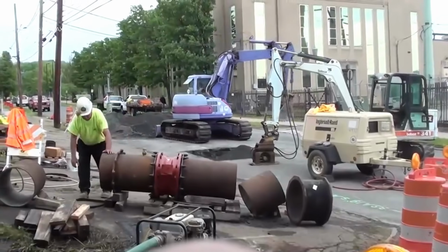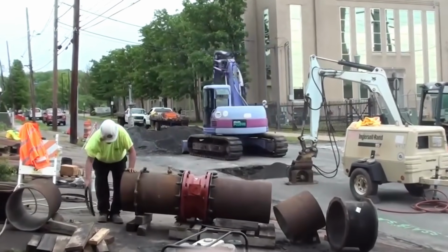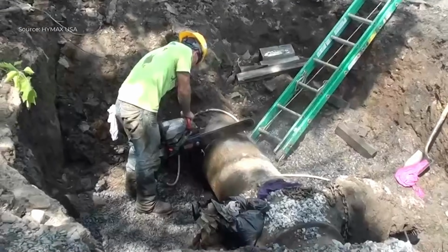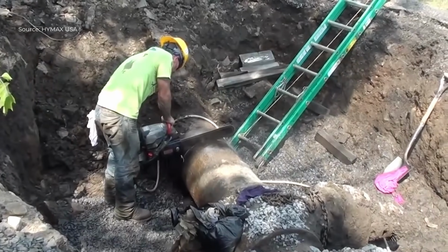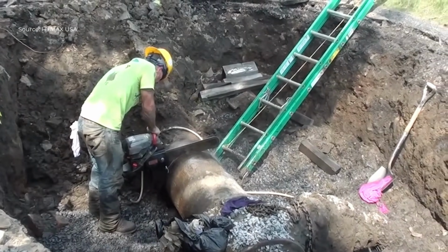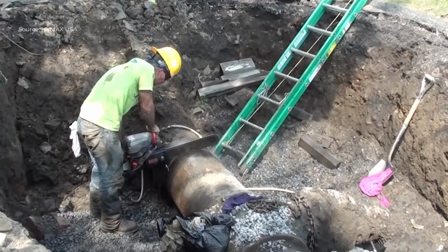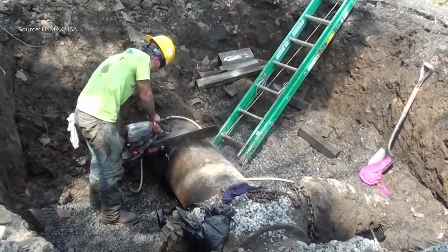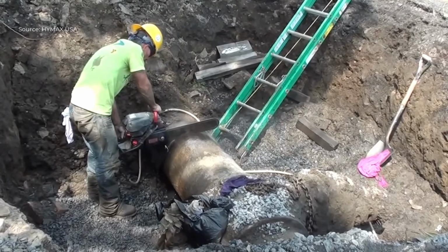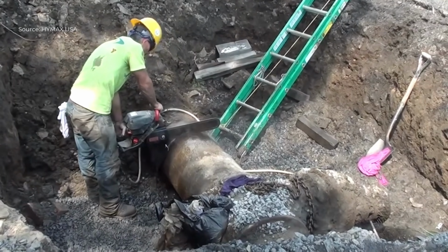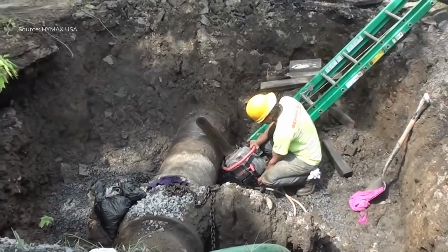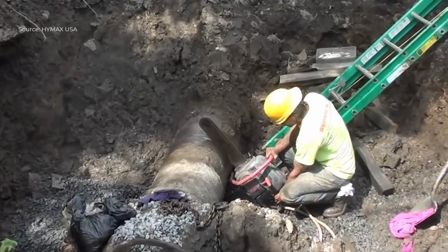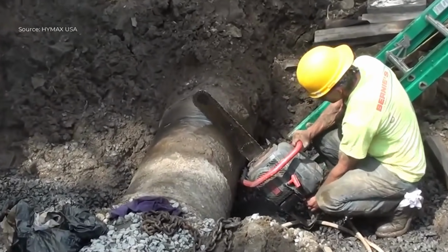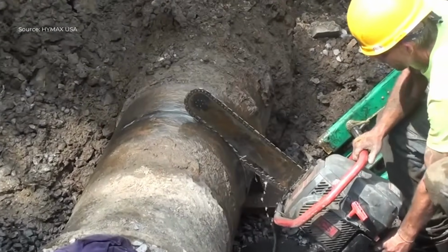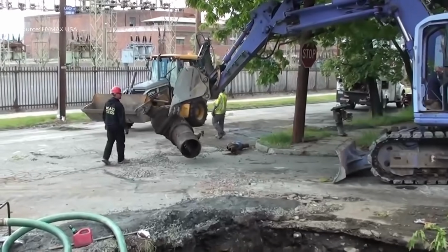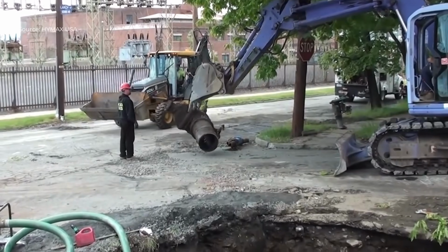The ruptured 18-inch cast iron main was first isolated by installing 3 line stoppers so water could be held back while work proceeded. A nearby hydrant and a leaking bypass valve were taken out of service and exposed. Crews then cut out the damaged section of pipe using a chainsaw fitted with a water spray to keep the thick iron cool during cutting.